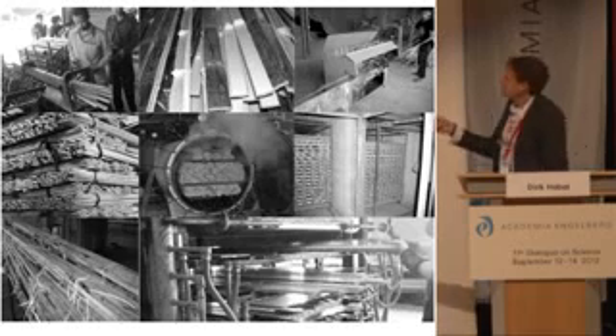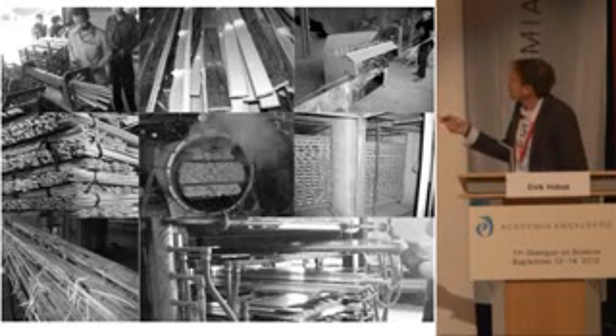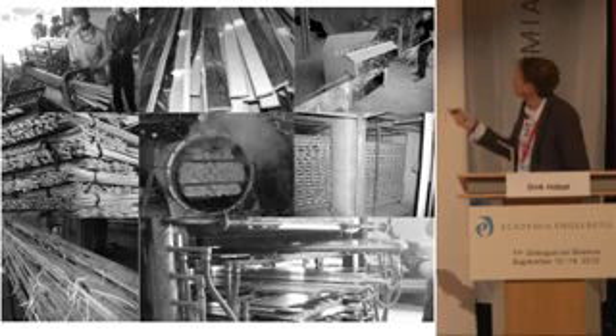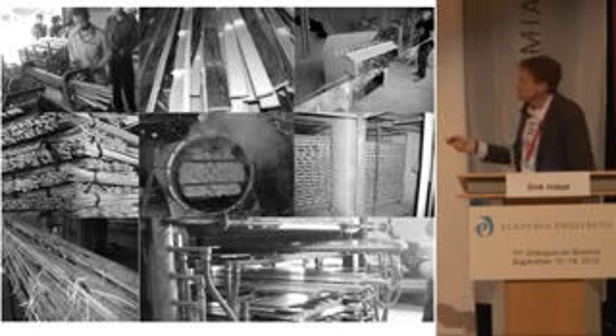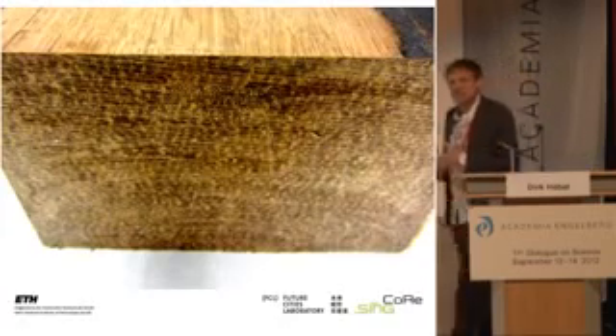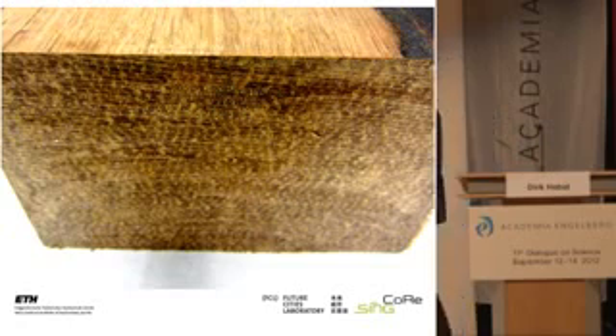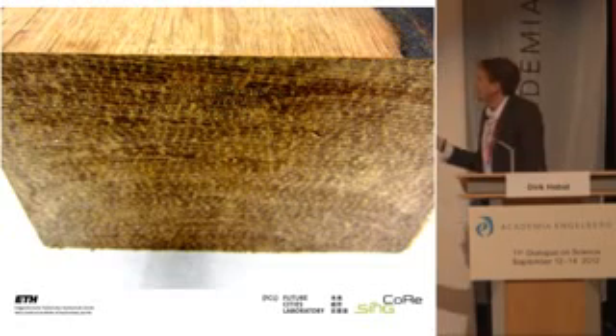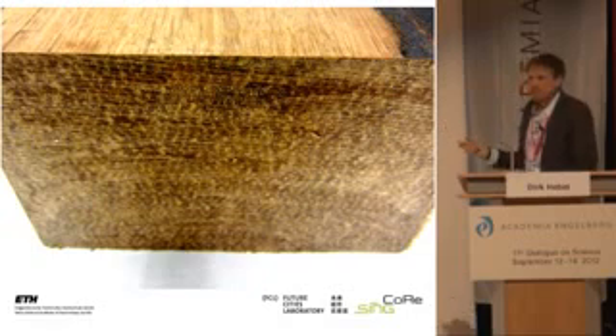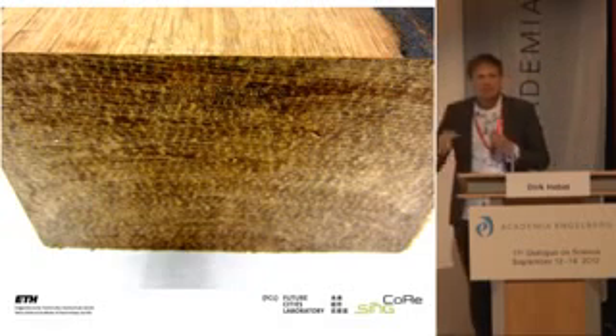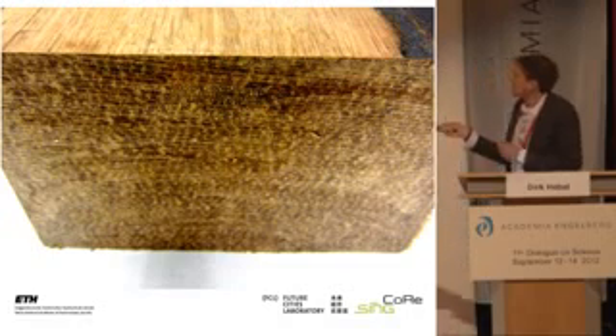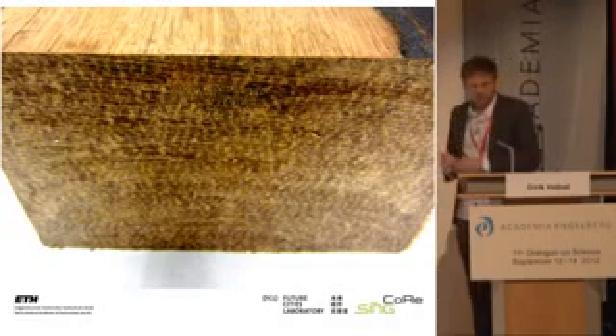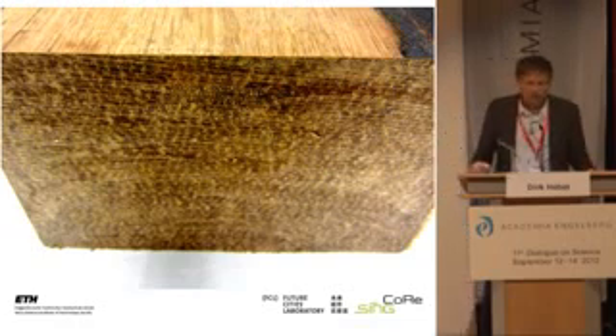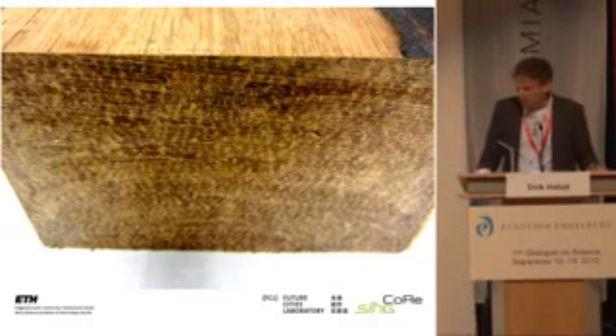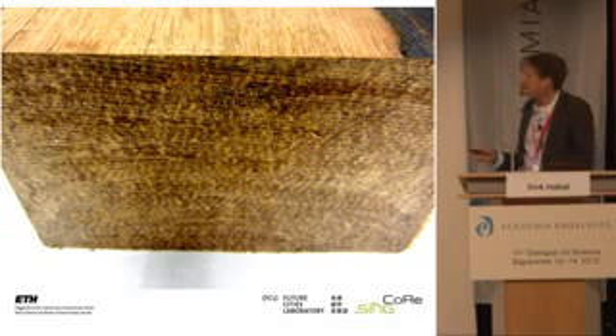So you see here the finished product. You maybe can recognize again the small bundles of fiber which are produced. It's a very, very dense material. It is compressed with a hot press. It is water resistant, so we do not have any problems anymore when the water comes to the micro cracks in the concrete. Plus, because the sugar is taken out of the material, we make sure that bacteria and other insects are not interested anymore in eating it.